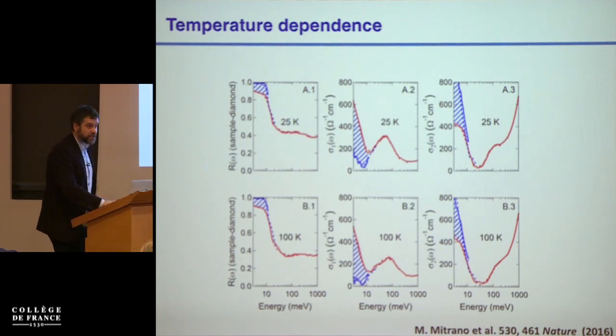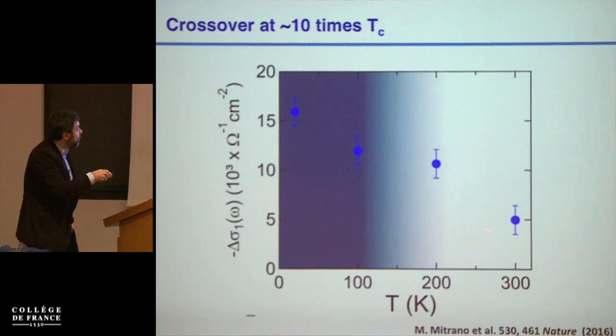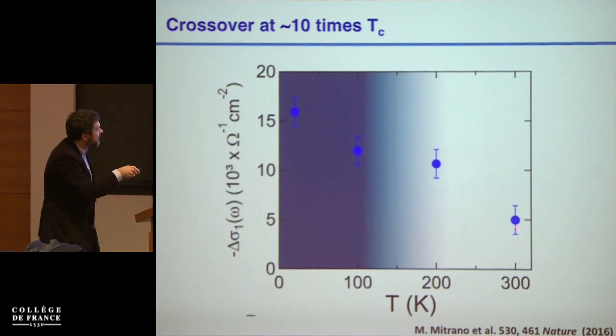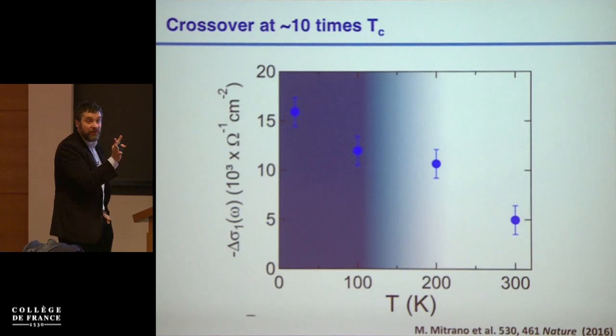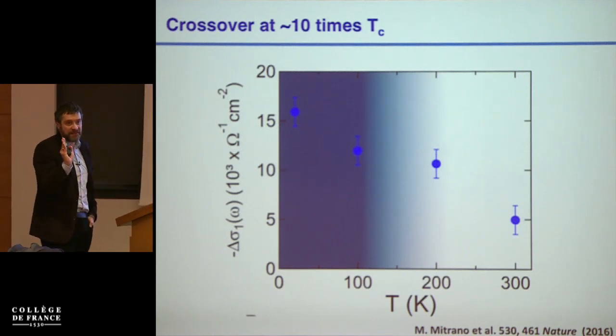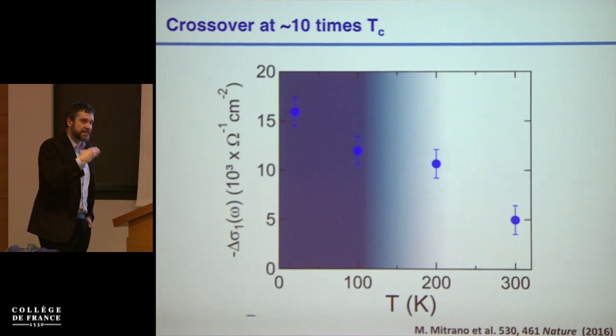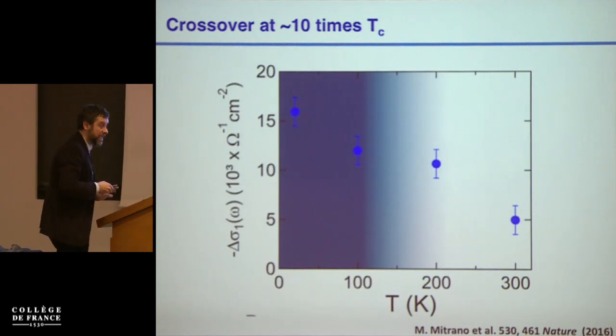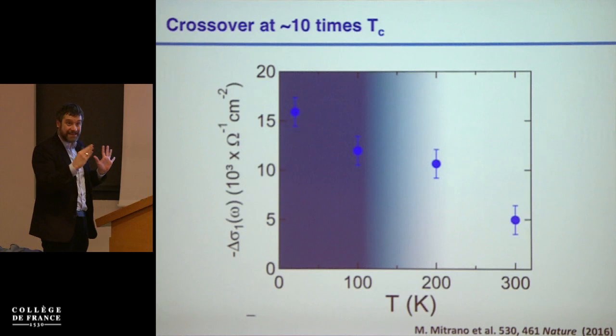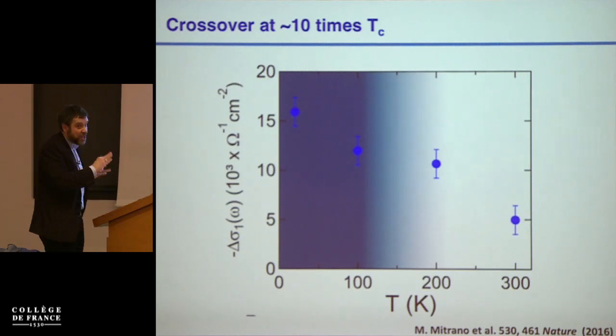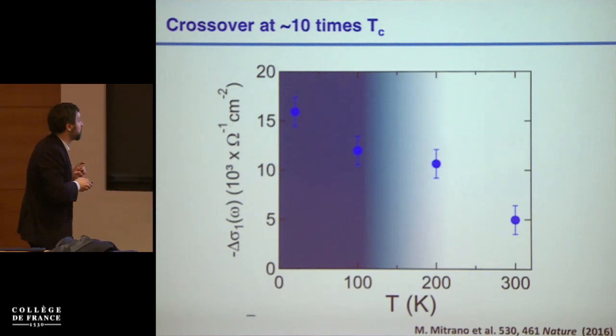And this effect, the opening of a small gap, is observed for all temperatures, up to even room temperature, although the gap becomes less and less convincing as one goes to temperatures higher than, say, 100, 150 Kelvin. There, in principle, one can fit the data with a Drude fit with a slightly better mobility than the equilibrium state. Okay? There are actually more recent experiments under static pressure that suggest that this state is not a trivial matter at all, and might in fact be indicative of some non-trivial coherence. Okay, but this is really a subject for a different and more specific lecture.